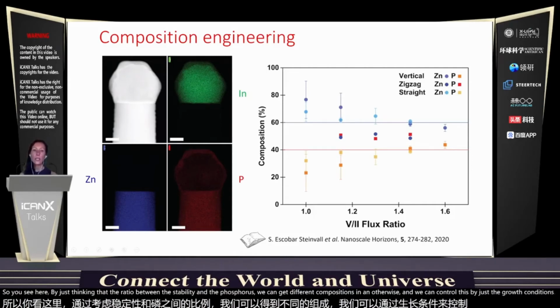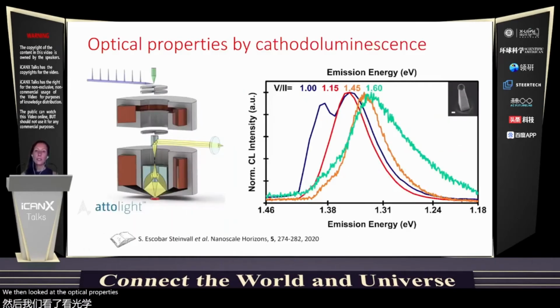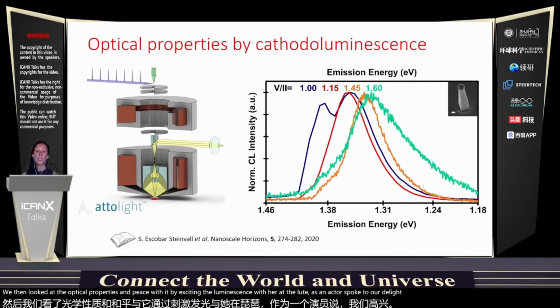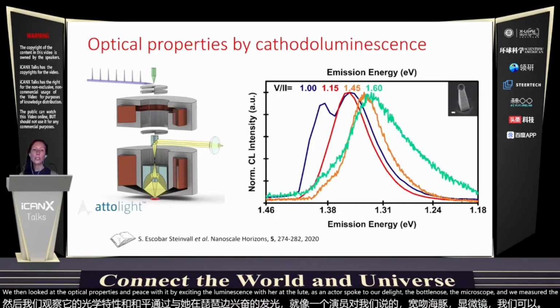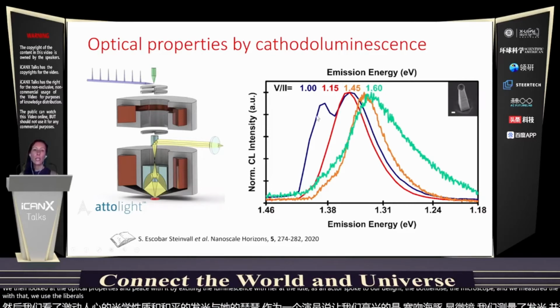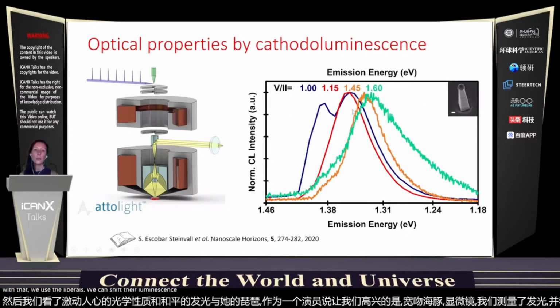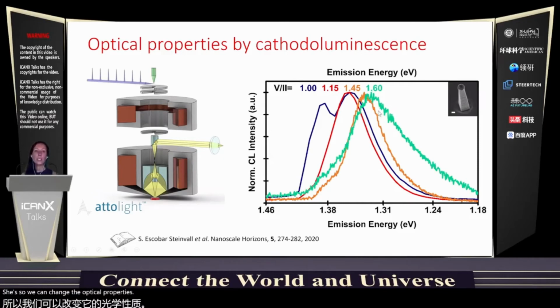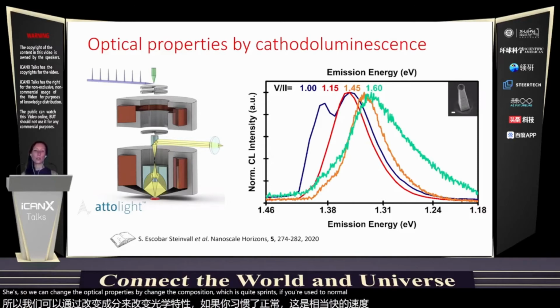We then looked at the optical properties, and this we did by exciting the luminescence with a cathodoluminescence microscope and a photoluminescence microscope, and we measured the luminescence. You see how, depending on the ratios that we use during growth, we can shift the luminescence peak over quite a broad range here. So we can change the optical properties by changing the composition, which is quite strange if you're used to normal compound semiconductors.